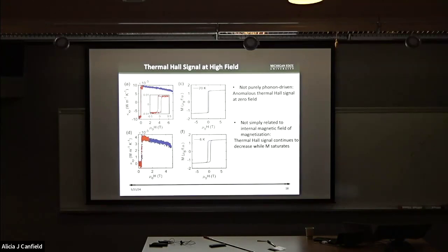The second possibility is that it's mainly driven by the phonon thermal Hall effect induced by the internal magnetic field of the magnetization, because the system is ferromagnetic. We could also exclude this possibility by comparing the field dependence of the magnetization and the field dependence of the thermal conductivity going to high field. When I go to high field, the magnetization saturates, while the thermal conductivity continues to decrease. So this immediately tells us that the thermal signal is not related to the internal magnetic field of the magnetization. Instead, it's something related to magnetic excitations. As I mentioned earlier, when we apply a magnetic field, the magnon bands are pushed up to higher energy. Therefore, the thermally populated magnons have a smaller population, and that's the reason we get a decrease in the thermal signal.